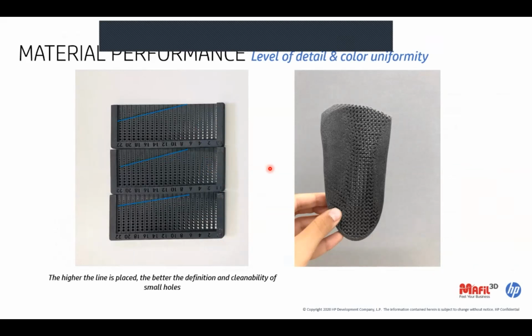When we are talking about elastomeric materials, we are mostly talking about different kinds of lattices. As we are willing to use this elastomeric material in certain manners, we are working on these kinds of complex structures, which we call lattices. With some other materials, it could be problematic to clean them properly. But this is not the case with our TPA, because the process is very similar to the PA family we have very good experience with. So you can see that even the cleaning of these complex structures is kind of easy. You can use the same process and same parameters as for polyamides,